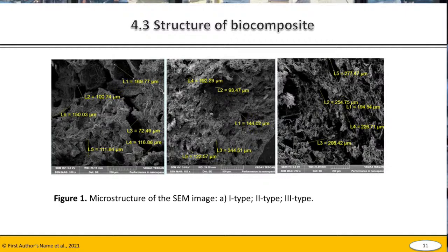In this picture, we can see the fracture surface of the samples investigated using the SEM. The photo shows the cellulose fibers lie well in the matrix. There is no pulling out of the fibers, and after the impact, there is brittle fracture without sign of plastic deformation in the material. Regardless of the porosity, the material exhibits quite good mechanical properties. Please, next slide.